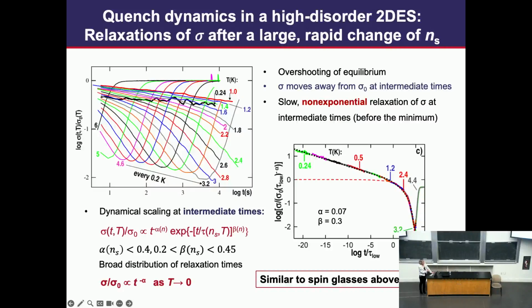So this is the range, depending on density - this is the stretch term. And then in spin glasses, this is typically what people get, and it just means you have a distribution of relaxation. Yes, but in our case, I think this is cool - it's just a power law in the zero temperature limit. But yes, it's similar.